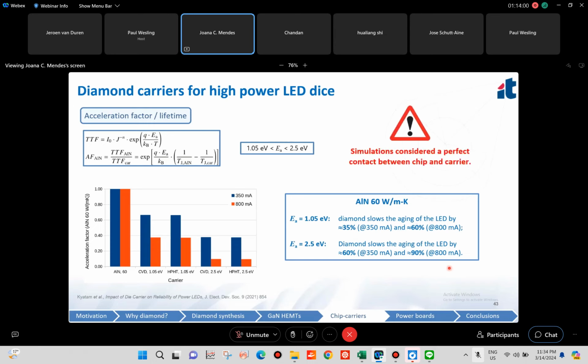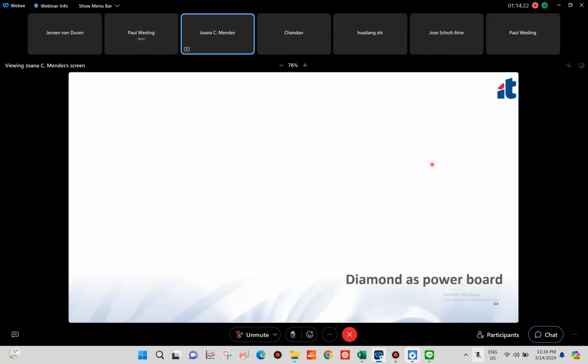However, we should take into account that the simulations consider a perfect thermal contact between the chip and the diamond carrier. Because if this doesn't happen, if we have a high thermal resistance at the interface, actually we cannot extract the heat from the die down to the diamond carrier. And after having seen these results, we decided to experimentally test the use of diamond as a power board.